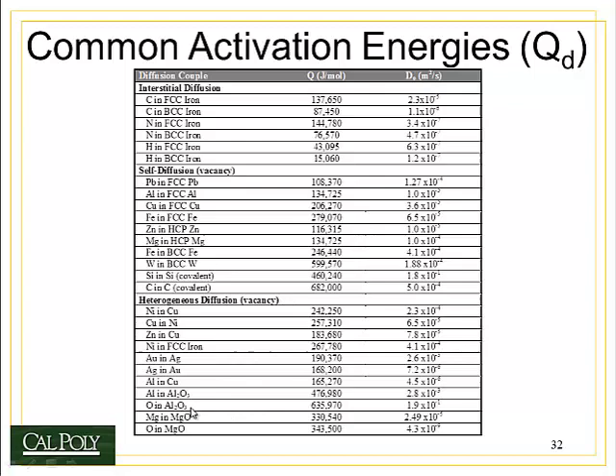Oxygen moving in aluminum oxide has an extremely high activation energy because the ionic bonds of aluminum oxide resist deformation and make diffusion more difficult. Aluminum does oxidize and forms aluminum oxide, but once that aluminum oxide forms on the surface, it is such an amazing barrier to the diffusion of oxygen that further rusting or corrosion cannot happen. A similar phenomenon occurs with magnesium oxide, although not as extreme as the case of aluminum oxide.